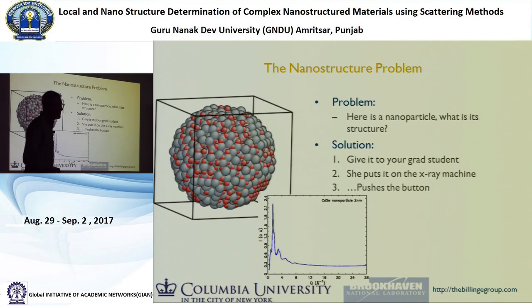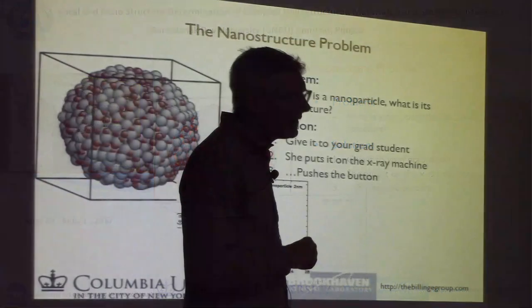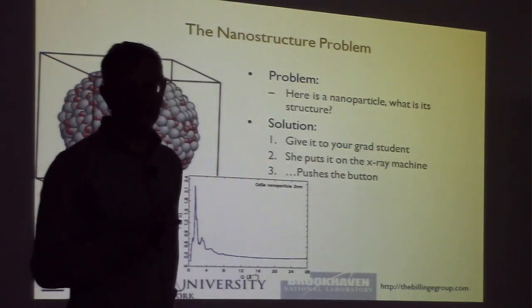And what's characteristic about this diffraction pattern is it looks like it doesn't contain much information. It only has like 1, 2, 3, 4, 5, 6, 7 peaks in it. And so the question is then, if your scattering pattern only has 7 peaks in it, and each peak contains roughly 3 bytes of information, right? The position, the width, and the intensity. So 3 sevens are 21, and some of these peaks are overlapped. So you've got somewhere between 15 and 17 bytes of information in this data set, and you need to solve a crystal structure from it. And it's hard. Basically, you can't.